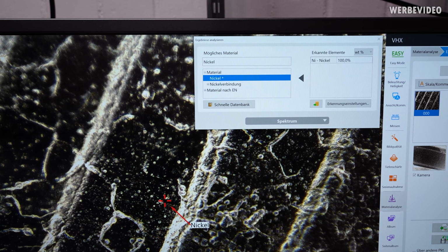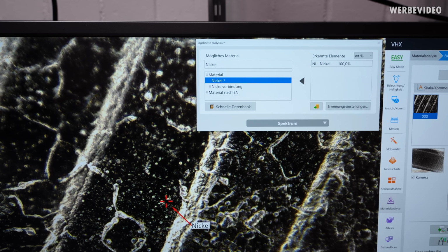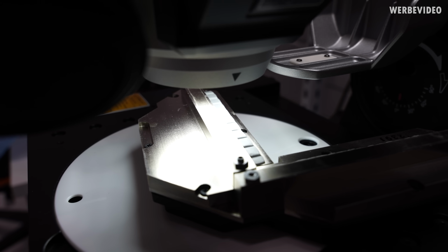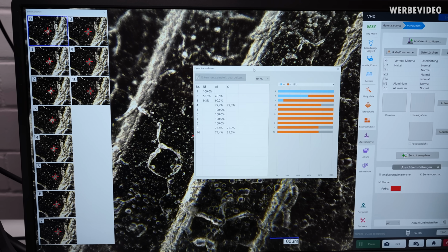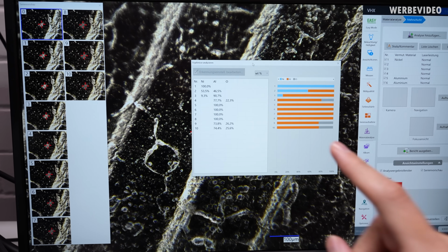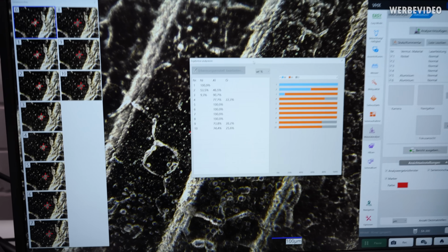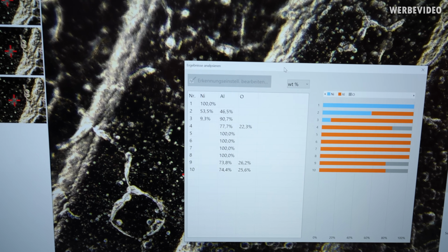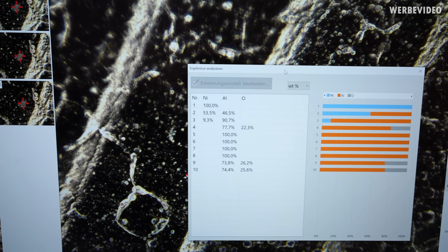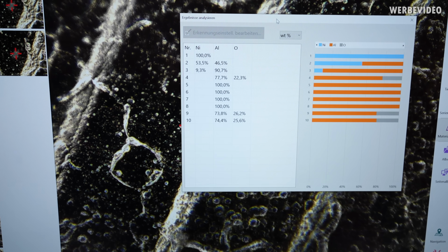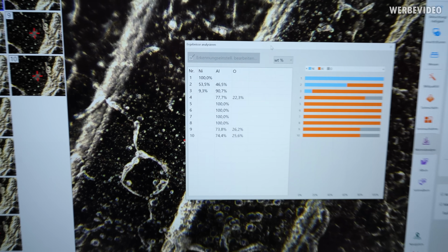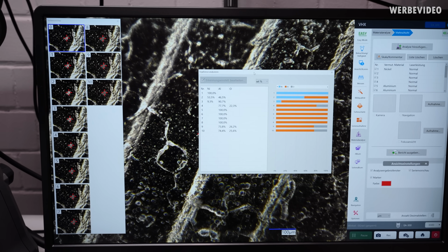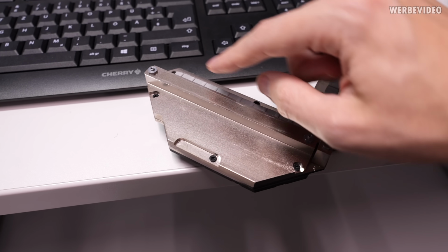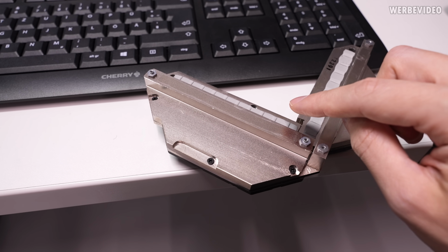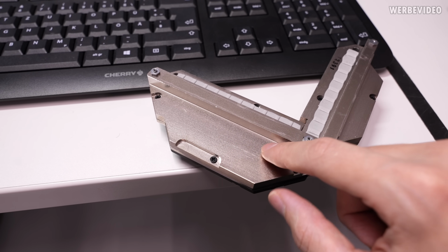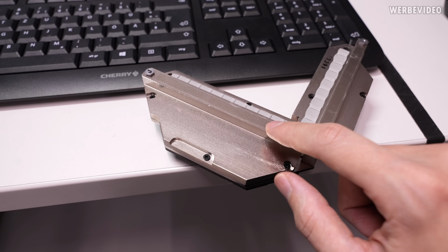But we will now use our laser to etch through the layer and see what we can find underneath. I repeated the test 10 times, so basically we have a laser shooting onto the surface, etching away some of the material, and then we can find this. So the first step was still 100% nickel, then it was a mixture of nickel and aluminium, and after that it was just purely aluminium with a little bit of oxide. So yeah, that is basically nickel-coated aluminium. So again, that was the area we were looking at. That's where usually a thermal pad is placed, making contact with the power stages, and that's also okay because this entire material would not have contact with the water.